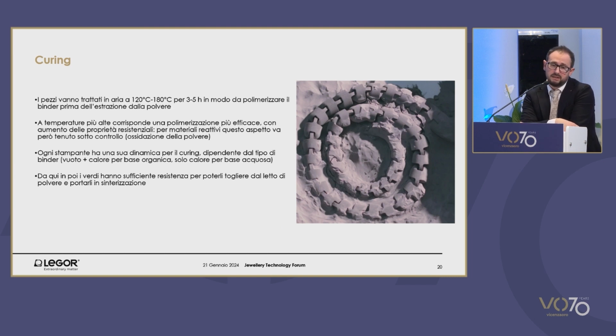The curing phase, which you saw before, during which the item is introduced in a chamber after being printed, envisages an intermediate temperature between 120 and 180 for 3 to 5 hours, depending on the quantity of powder that has to be cured.